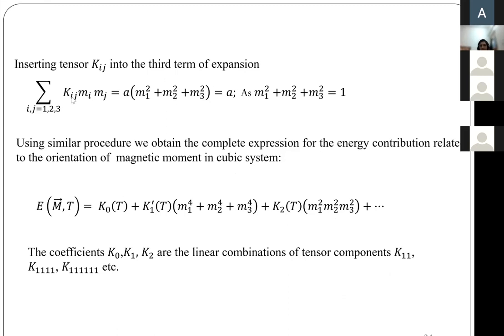Once we use this result in the second term, Kij Mi Mj, we notice that it is only non-zero when i is equal to j. So we will have K11 M1 square plus K22 M2 square plus K33 M3 square. But we found that K11, K22, K33 are all equal, so we just get A times M1 square plus M2 square plus M3 square. Notice that M is a unit vector, so this is simply a constant. The second order term just reduces to a constant. That is why in the magnetocrystalline energy there is no second order term. It is just submerged into the constant term.